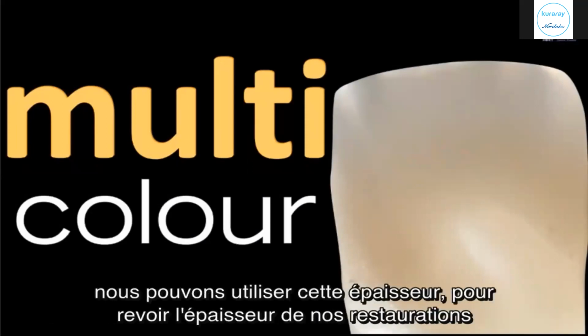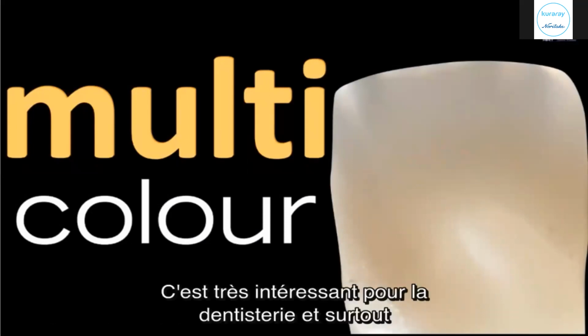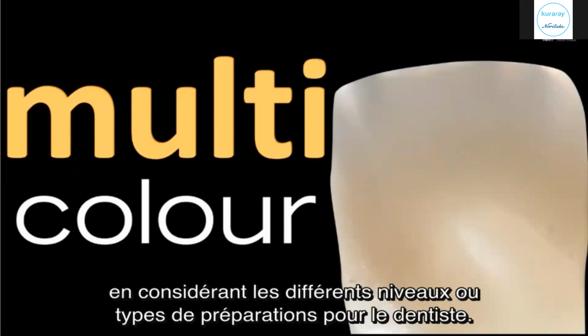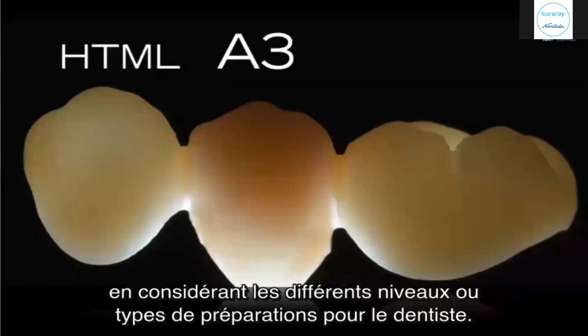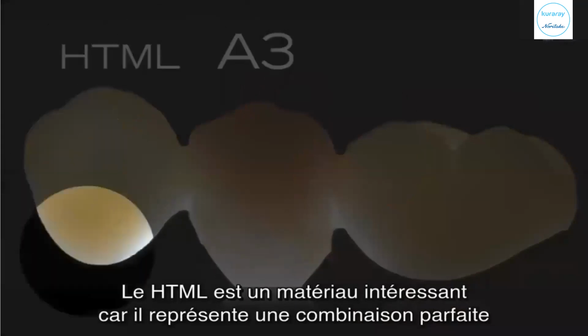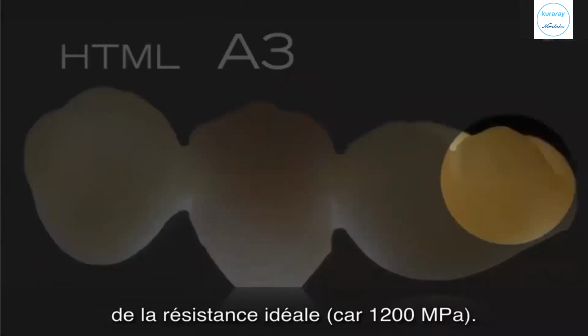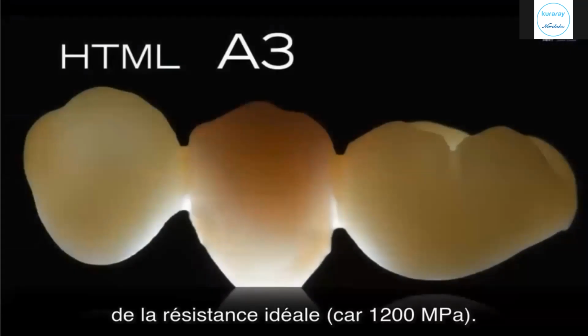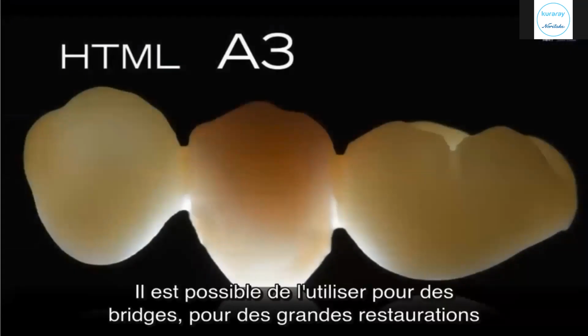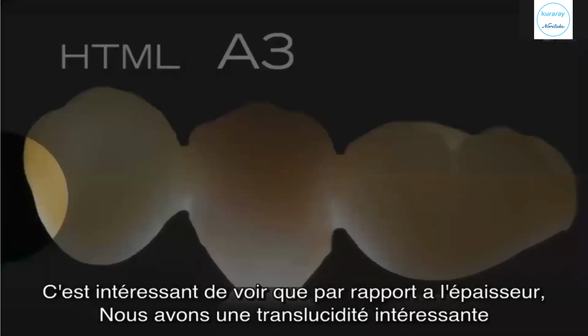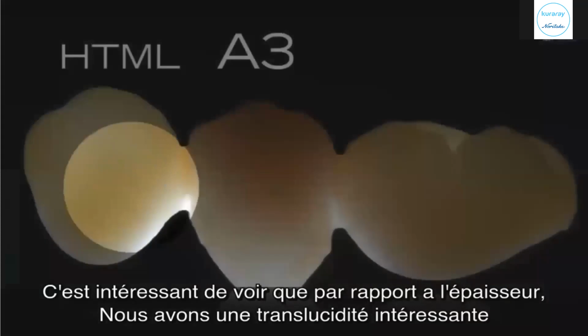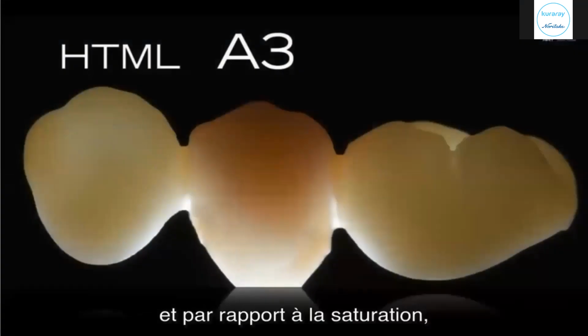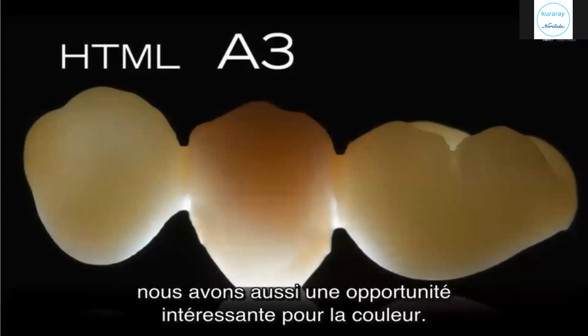Consider another aspect. We can reduce the thickness of our restoration. A really interesting aspect for dentistry, and most of all, consider the different levels or kinds of preparation for the dentist. So the HT multi-layer is an interesting material because it represents a perfect combination, with ideal strength of 1,200 megapascal, possible to use for bridges and big restorations. But it's interesting to consider also, according to the thickness, the interesting translucency, and most of all, according to the chroma, we can now also have a very interesting chance to match the color of the patient.